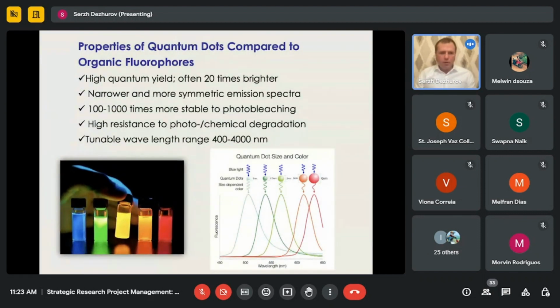The fourth property is a high resistance to photo and chemical degradation. The same oxygen or other active species couldn't affect quantum dots if you create a good shell for your quantum dot. The fifth is tunable wavelength. The range is very big, from deep ultraviolet, from 100 nanometers to 4 micrometers. It depends on the composition and size of a quantum dot.